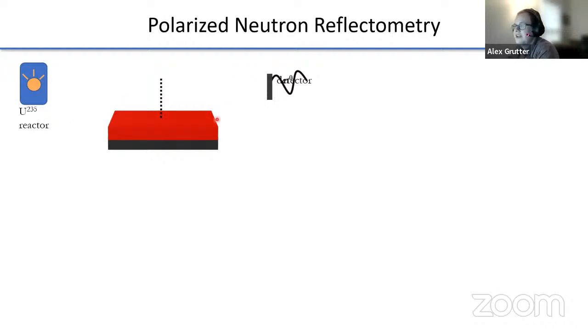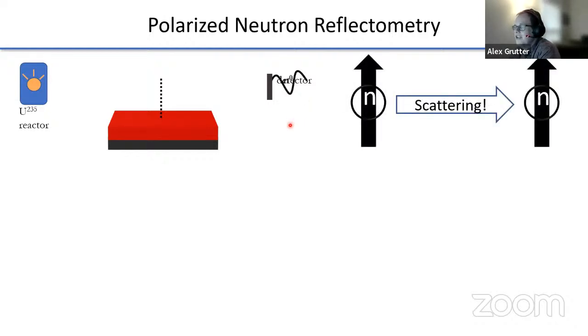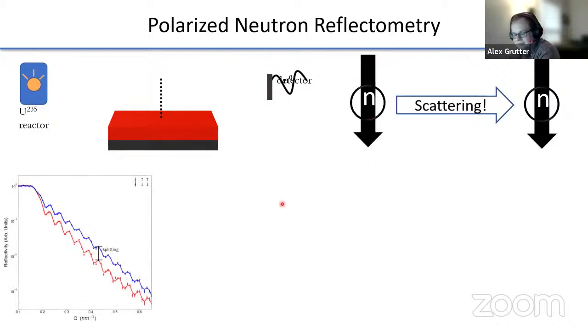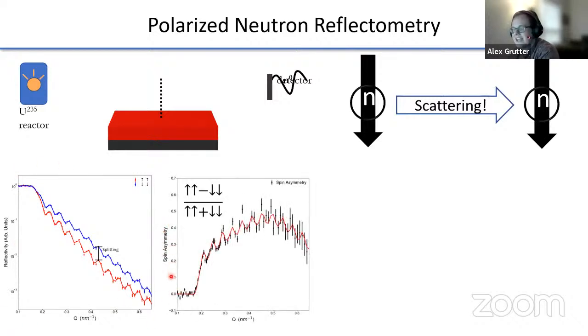And then you collect that reflected neutron in a detector. And you do this with spin polarized neutrons. So you look at the spin up reflectivity, you look at the spin down reflectivity. And hopefully, if you have a magnetic sample and you collect the reflectivity as a function of angle, you will see a splitting between your spin up and spin down reflectivities. And so we can plot it like this, or we can look at what we call the spin asymmetry, which is just one minus the other divided by their sum.